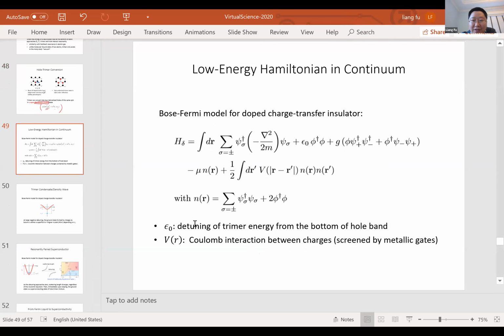So this leads us to this universal model for doped charge transfer insulators. We have psi, which labels the itinerant holes, and near the band bottom they have a parabolic dispersion. They have a valley index. This phi denotes the trimers, and its energy relative to the bottom of the hole band is denoted by epsilon naught. And there's a conversion, a trimer can be converted into a pair of holes. And finally, there is an electrostatic interaction between charges. The charge density is given by the charge of the holes plus twice the number of trimers. Each trimer carries charge 2e. So this is our low energy Hamiltonian in the continuum limit.